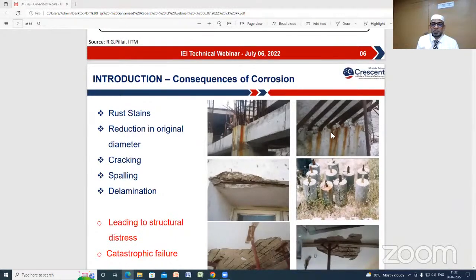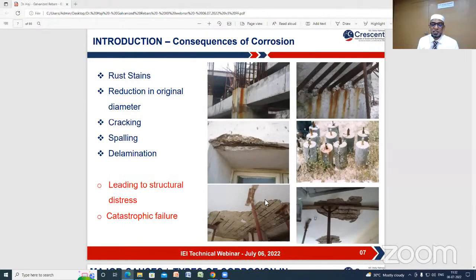These are pictures or photos from some of the ongoing projects. You can see that the rebar has already started corroding. Even if you use durable concrete or sustainable concrete in this, it won't serve its purpose. Already rust stains are running down, and definitely there will be a reduction in the original diameter. If you use these without taking care of the corrosion aspects, within 5 to 10 years these things will happen. There will be spalling, cracking in the RCC members, delamination, which will lead to structural distress and sometimes catastrophic failure. As we see in the newspapers, every week we are seeing some catastrophic failure, a building collapse without any warning.